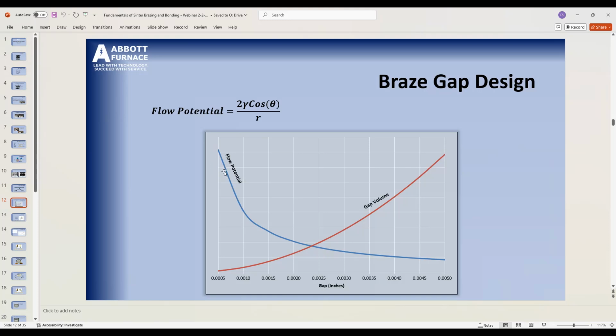If you look at the size of the pore, our porosity versus our gap size, the tendency to pull the filler metal through is this blue line, and the volume you're trying to pull through, or the weight, is the red line. You notice right here where it crosses is right around 0.002 of an inch. That's your optimal gap. 2 to 2.5 thousandths will give you the most filler metal with the fastest pull. Once you get a larger gap, you can't pull it through.